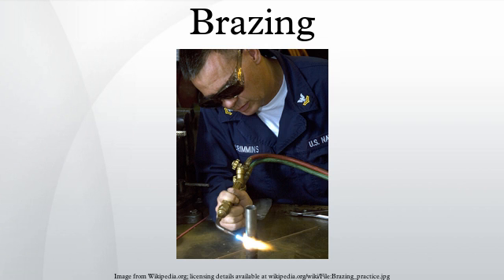Dissolution of base metals can cause detrimental changes in the brazing alloy. For example, aluminium dissolved from aluminium bronzes can embrittle the braze. Addition of nickel to the braze can offset this. The effect works both ways. There can be detrimental interactions between the braze alloy and the base metal. Presence of phosphorus in the braze alloy leads to formation of brittle phosphides of iron and nickel. Phosphorus-containing alloys are therefore unsuitable for brazing nickel and ferrous alloys.